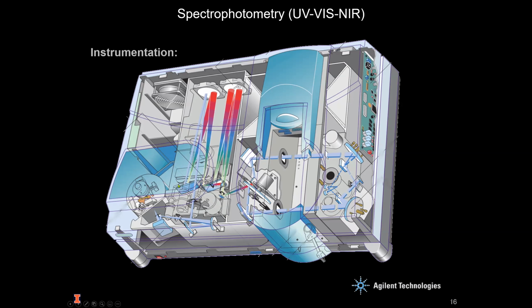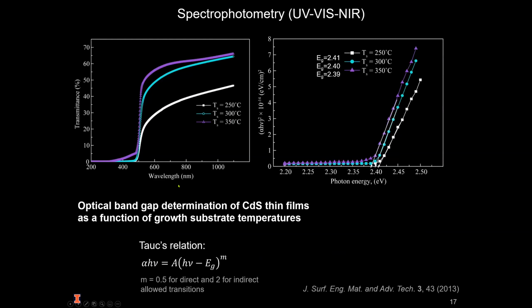Since UV and visible photons have energies matching those of electronic transitions in materials, spectrophotometry can be used to determine the electronic band gaps of these materials. So from the transmission or reflection spectrum of the material, we can determine the absorption coefficient, and then using Tauc's relation, we can calculate its band gap. Here, the band gap of cadmium sulfide was determined for different substrate growth temperatures, giving some insight into the growth process of that material.